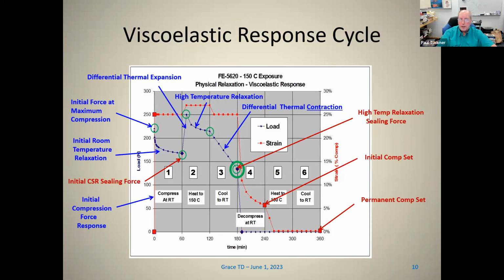When you stabilize at a high temperature, it'll begin to show relaxation at that point. Then if you cool it back down, you'll come to a point which will have a sealing force lower than your initial drop from the initial relaxation. This has to do with the high temperature relaxation that occurs just from exposure to the high temperature.